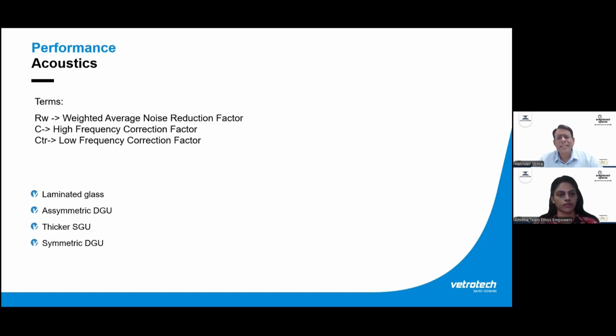Very important, these fire rated glasses, when used, really give you an acoustic benefit, because let's say there is a partition and you have to use a fire rated material over there, and if it is glass, specifically these interlayered glasses, they give a very good acoustic benefit. They give Rw close to 38 decibels, and it can go higher also based on different combinations. So we really have an advantage of acoustic benefit when we use these fire rated glasses.